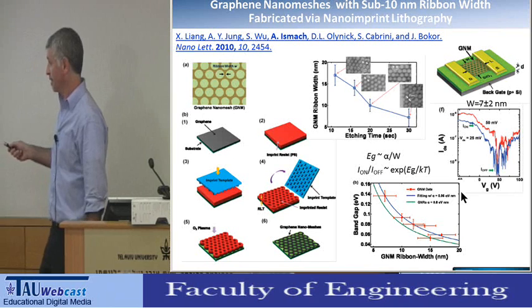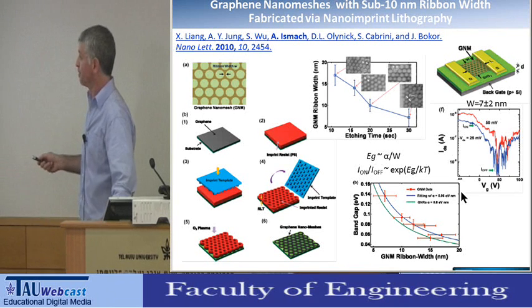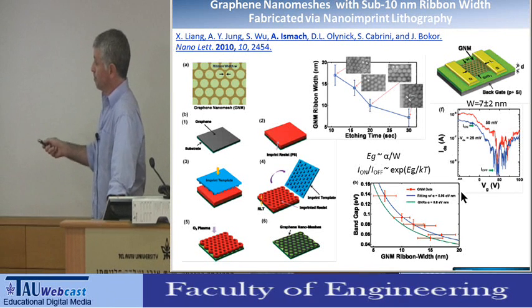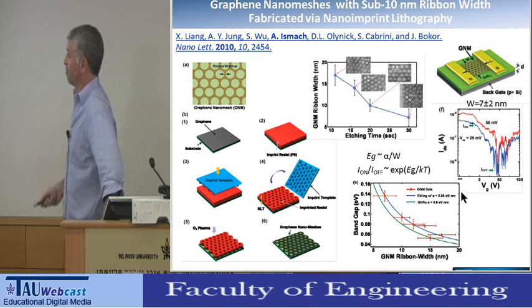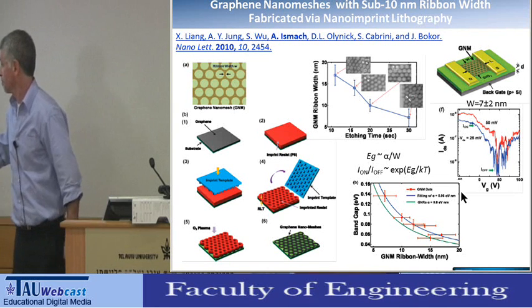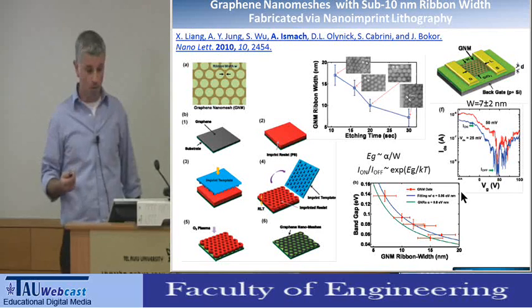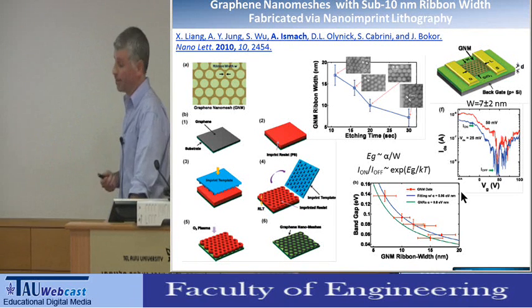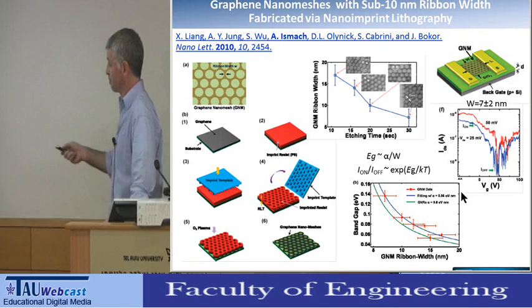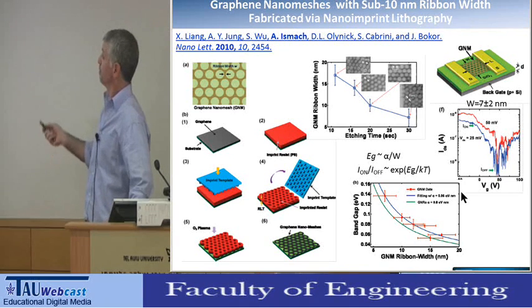And then the on-off ratio is related to the band gap with this formula. So then you can see that it is, of course, related also to the width. So by controlling the width of the nanoribbon, you can control the band gap and, of course, the on-off ratio of your final device.